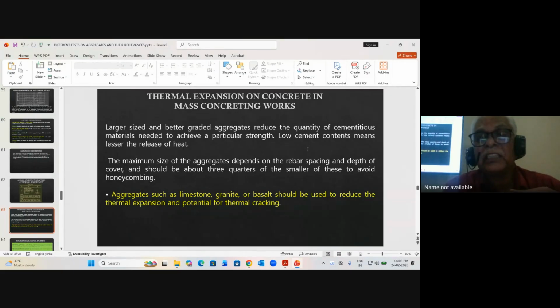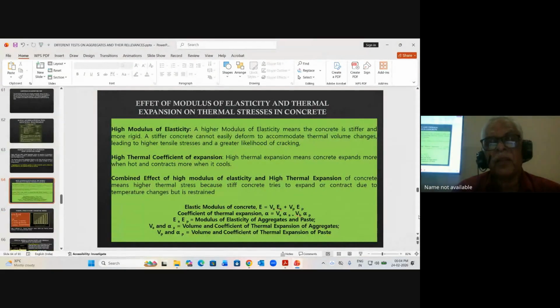That is possible with less cement content. Less cement content is possible only with higher size aggregate, which requires less cement content because its coating surface is relatively less compared to lower size aggregate. With lower size aggregate, more coating has to be done with cement - more cement coating means more cement content, and more cement content means higher release of temperature. So higher size aggregates are desirable.